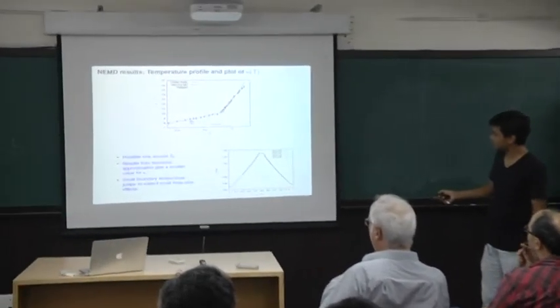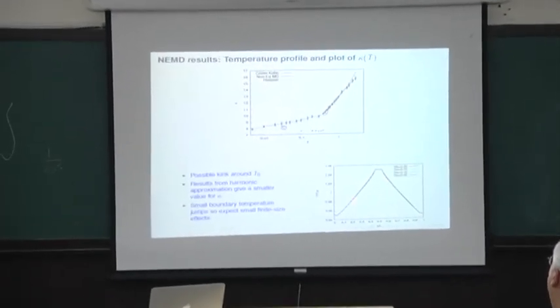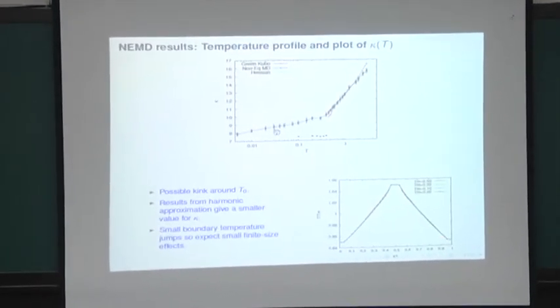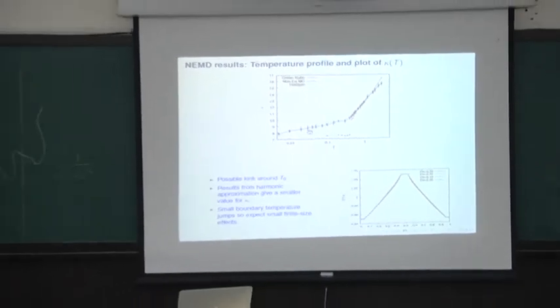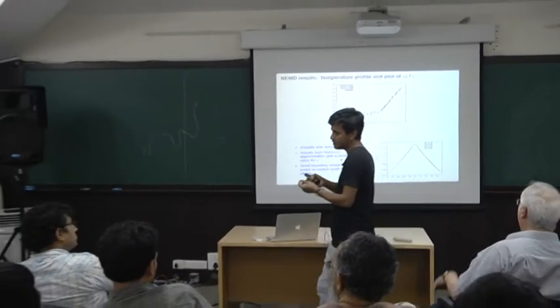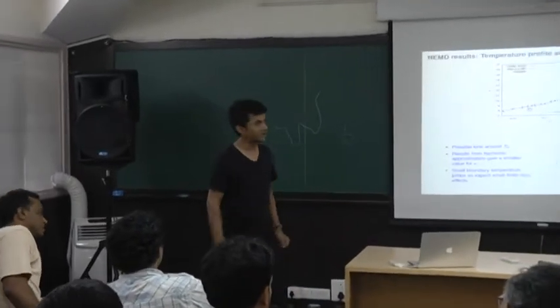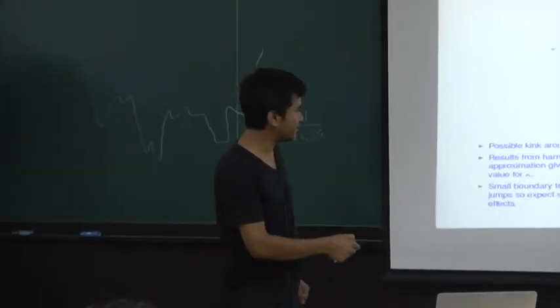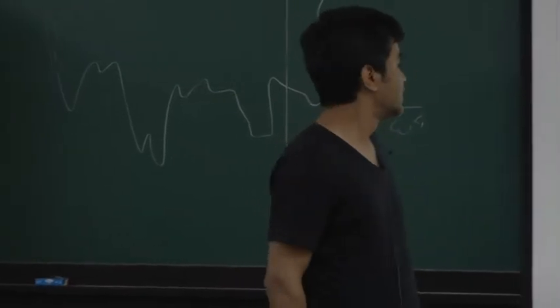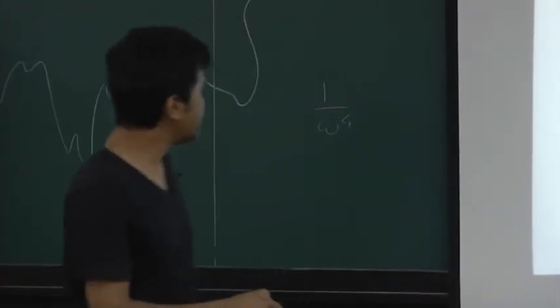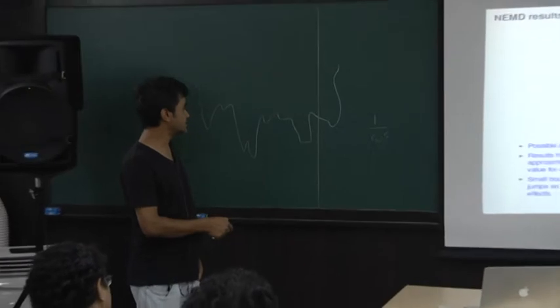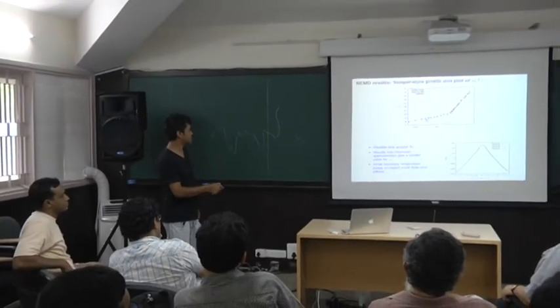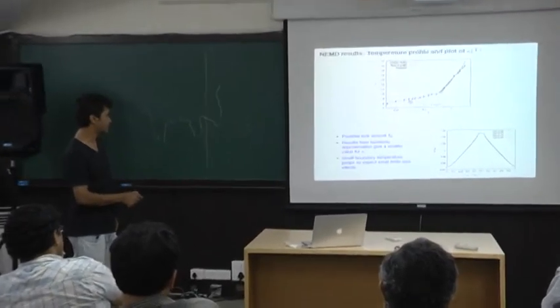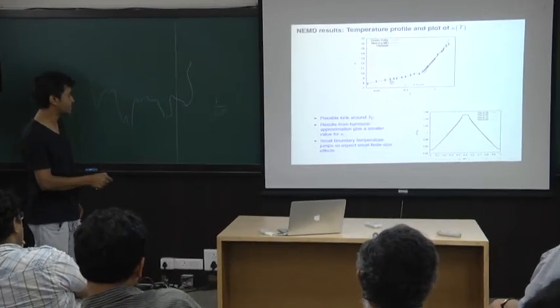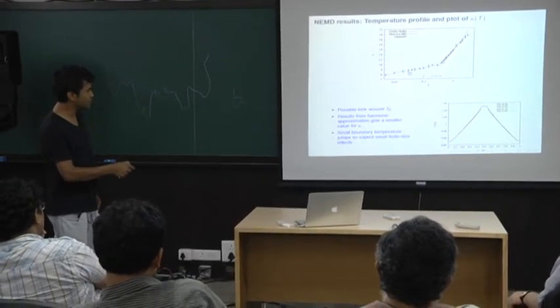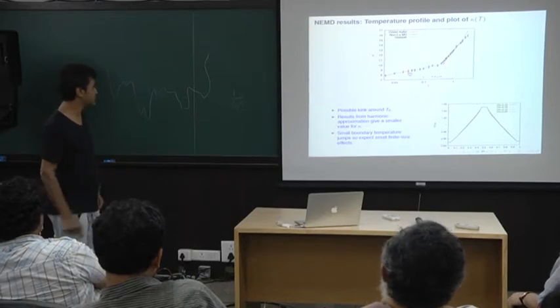The other thing is if you look at the temperature profiles, this is one I've just scaled by the mean temperature, and all of them look very smooth. So it looks like things have equilibrated in that sense at least. At least the local temperatures are well defined, even at very small temperatures. So the main thing we see is a possible kink around this. These results are still very preliminary. Results from the harmonic approximation give a smaller value of kappa. So maybe if you really go to very low temperature, they will meet.